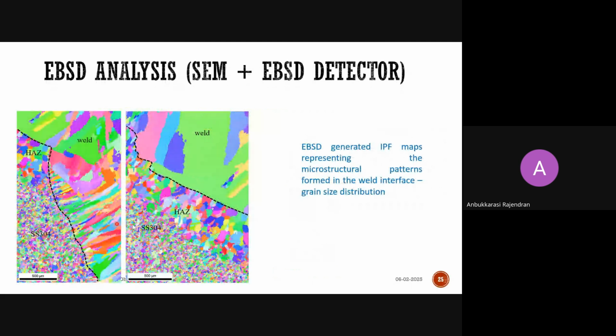This is one of the dissimilar weld samples, the same sample I showed in optical. This is the nickel side, this is the 304 side, and this is the heat affected zone where coarser grains are seen. The weldment shows dendritic grains, coarser in size, very huge grain size, and the heat affected zone is coarser than the base metal. This is the typical base metal, which has a very fine grain size.